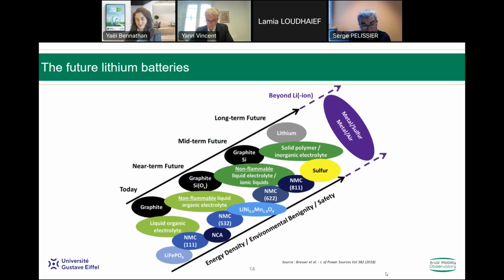Here on this slide, you see at the beginning that today's technologies use graphite for the negative electrode, and you can see what I previously presented, the LFP, NMC, and NCA technologies. Between them you have the liquid organic electrolyte, and these are the present technologies. People expect that in the future, concerning the negative electrode, you will find more and more silicon. In the positive electrode, you will find some variation in the NMC composition with more nickel and less cobalt. And in the far future, people expect to use lithium metal with a solid polymer and inorganic electrolyte.